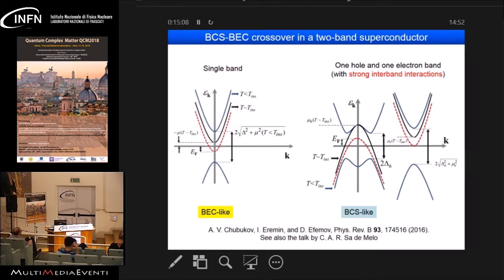And what they found is that they consider one hole band and one electron band, as shown by this dashed red curve, in the beginning. And they consider very strong interband interaction between these bands. And then they put the delta over EF as a large number, and they calculate the electronic structure like this.